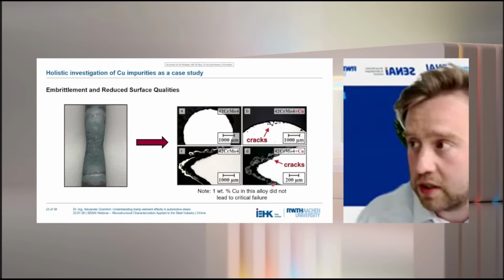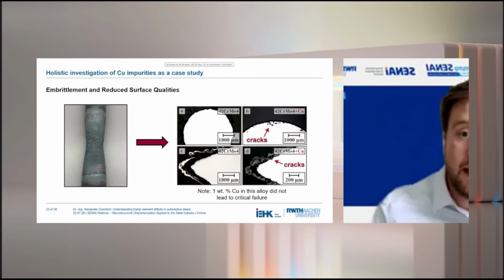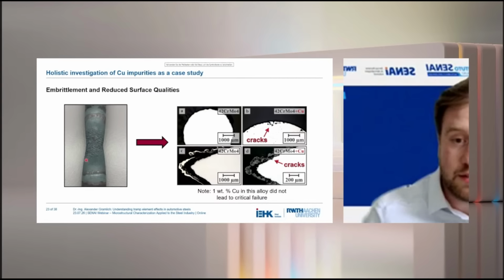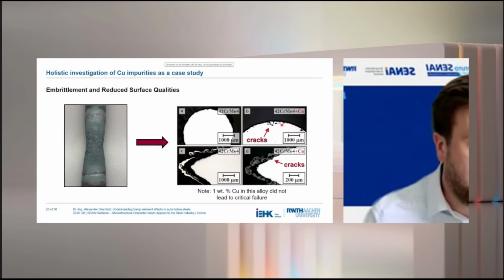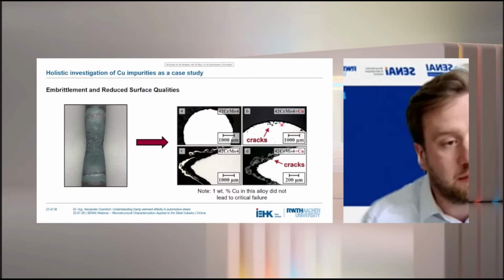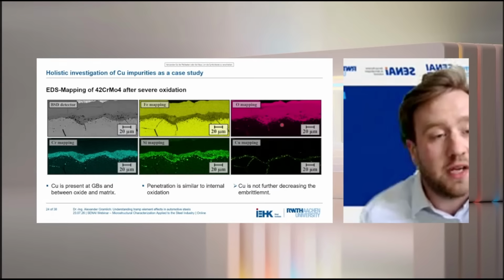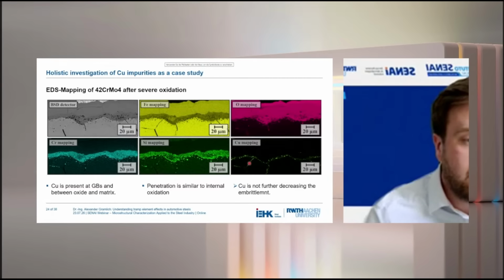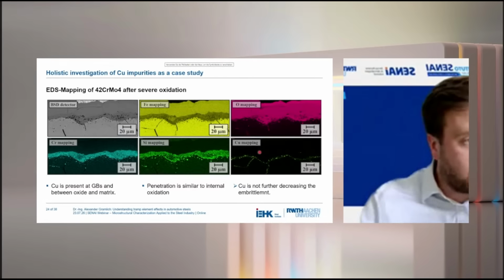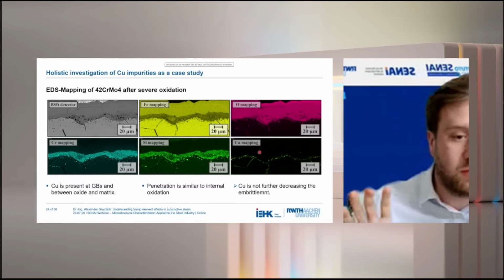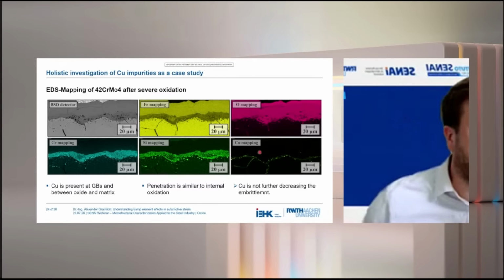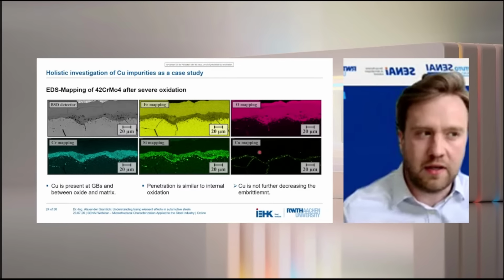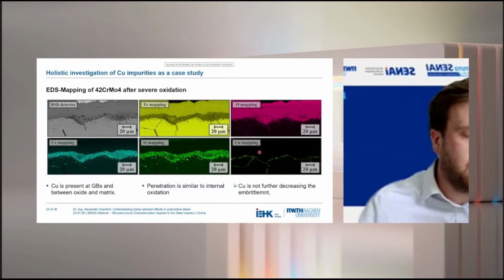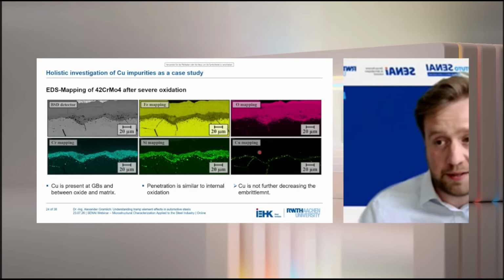Just to give you an example how this would look, in a steel sample, we did an interrupted hot tensile test, and here you can see nicely how basically the full surface of the sample is covered with deep cracks. And when you are then looking at microstructure images from the side, you can see that we have also penetration of these cracks into the steel sample. And when we are then looking into EDS mappings, we can see in this picture here that there is a lot of copper enrichment. So this is ongoing research at the Institute, especially to standardize the testing for the affinity to hot shortness and to give industry basically a way of finding out which copper concentrations are still possible to be produced in a certain steel grade.